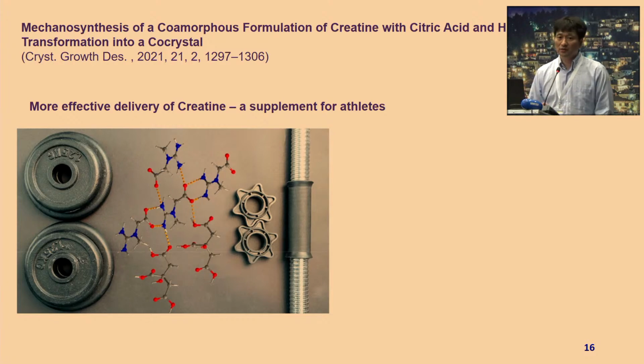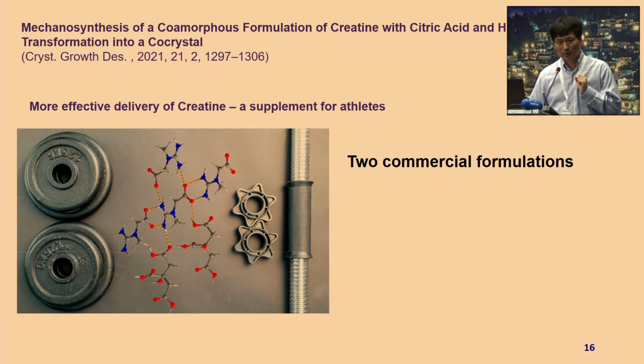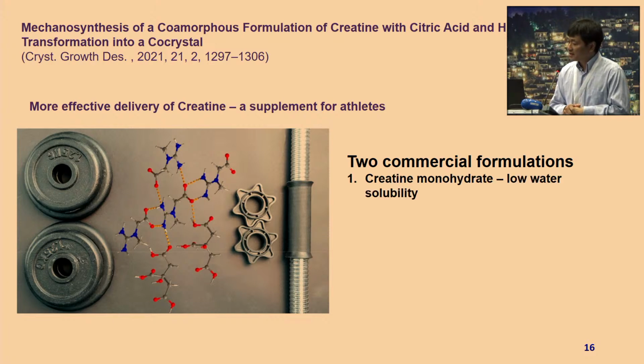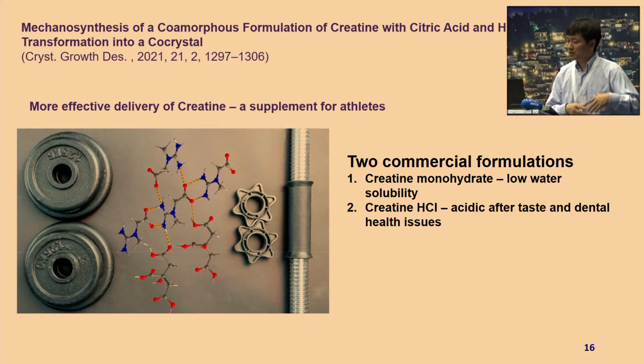Creatine is one molecule beneficial for athletes to build strength and muscles. But on the market, there are two commercial products of this molecule. One is the monohydrate, but it has a low water solubility. As you know, when the solubility is low, the absorption is slower, so it's not as effective. In order to overcome this issue, other people use the hydrochloride salt of this molecule. So it dissolves faster, but you also have the acidic aftertaste, so it's not pleasant. And also HCl is a strong acid, which has potential damage to dental health.